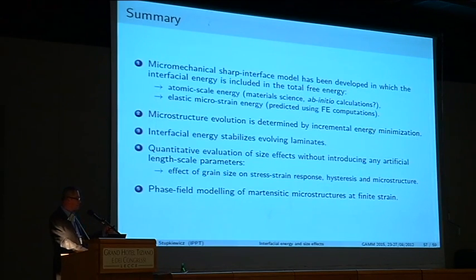Okay, so this brings me to the summary. I have shown you a micromechanical sharp interface model. In this model, we include the interfacial energy at different scales, in particular of two origins, the atomic scale energy and elastic microstrain energy. In this modeling approach, the microstructure evolution is determined by incremental energy minimization, a very general framework, but one that finds very good application here.